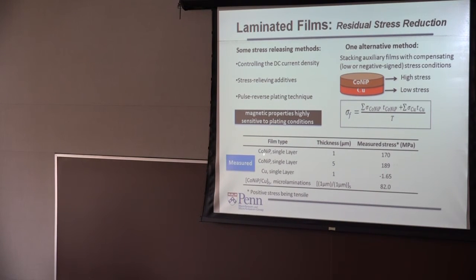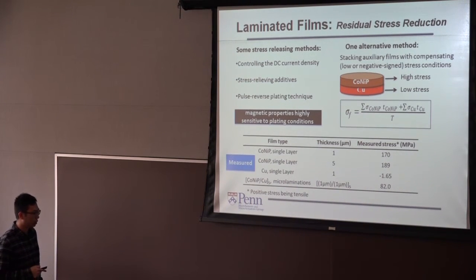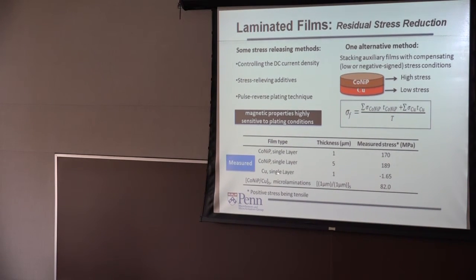We measured the residual stress of a single layer and a multilayer structure with a profiler based on the Stoney equation, utilizing the film curvature. As you can see, the relatively low stressed copper single layer reduces the average stress of the cobalt nickel phosphorus to almost half of the 1 micron single layer and the 5 micron single layer. And note that the measured stress is very close to the prediction, with an error of less than 2.5%.